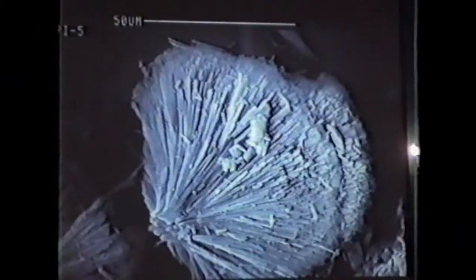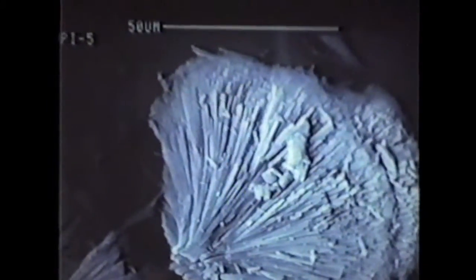When you look at the material, here is an SEM. It's a 50 micron bar. You see that the morphology is needle-like, and if you look down the needles, you'll look down the big pores. You're looking down the Z-axis, and they grow in aggregates. Sometimes you see them in these fan-like aggregates, and also you can see twisted double fan aggregates here.